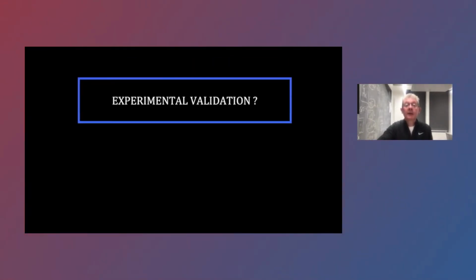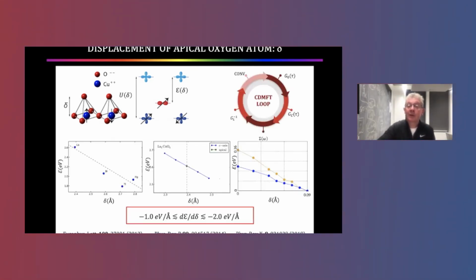All right. Now, how could you test this idea? Well, the first thing you need to do is to change the charge transfer energy. So that's a tricky one. But Gabby Kotliar and his team identified how to do that. You can do it by altering the distance of the apical oxygen atom from the copper atom. The apical atom is minus 2e charged. If you move it closer to the copper atom, it drives up the charge transfer energy, and farther away, it drives it down. DMFT has revealed this for a wide variety of different compounds.